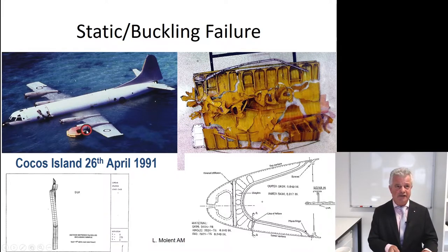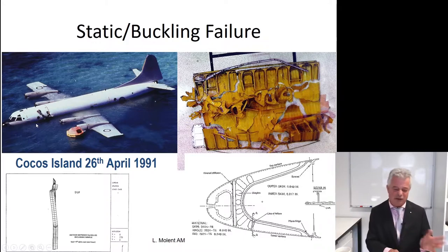More pertinent to my investigation, if you look carefully, the leading edges, the brown bits at the front of the wing, are missing, okay? And I can tell you we recovered those back along the flight path. Subsequent investigations revealed that the leading edges departed the airplane, rolled over and smacked the tailplane. In fact, one of them embedded in the tailplane, which made it even more challenging for the pilot to control. Not only that, it led to aerodynamic flutter to the degree that the environment in the cockpit was plus or minus 10 G. Pretty severe. Unfortunately, the airplane was flying like a brick, so it couldn't come back to the runway, but it slowed down and the flutter stopped, which enabled the pilot to ditch the airplane safely.